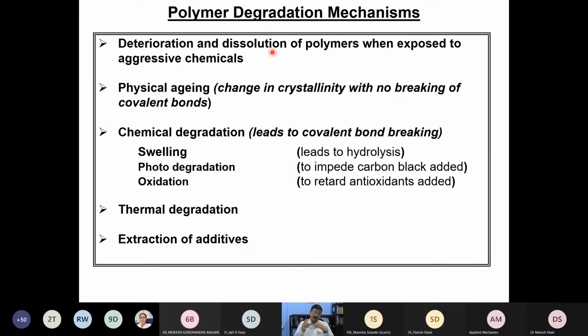This physical aging is really good from the mechanical properties point of view. The stiffness of the material is going to increase. The strength of the material is going to increase. But sometimes it is also transforming the material failure from very ductile to very brittle nature. That's not a good sign, because the polymer may break without giving any signs of failure. And as I mentioned, as crystallinity increases, the diffusion coefficient is also going to go down. From the contaminant perspective, that is always good.